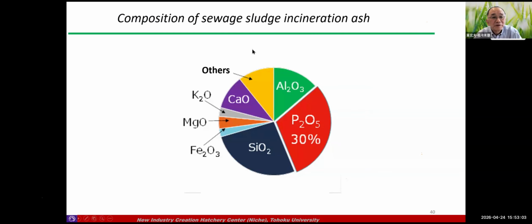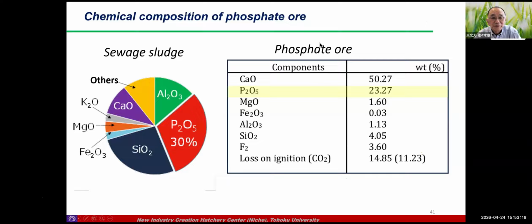So how to do that? This shows sewage sludge after incineration. We get ash, and the composition is something like this. This contains about 30% P2O5. Compared with phosphate ore, it is very comparable, sometimes even larger. But the point is, phosphate ore contains only a small amount of Fe2O3, alumina, and silica, but sewage sludge has a huge amount of SiO2, Al2O3, and Fe2O3. These compound oxides make it difficult to recover phosphorus.